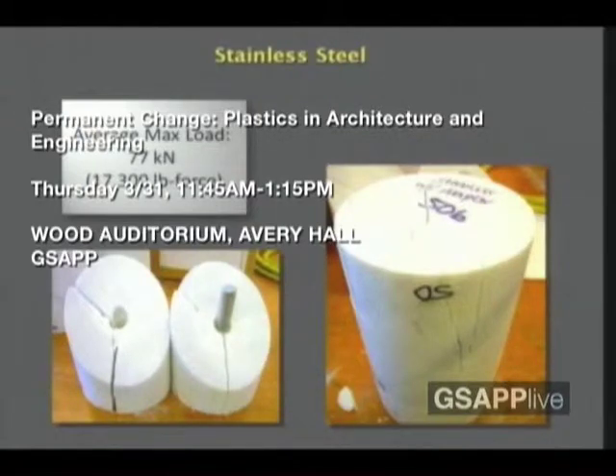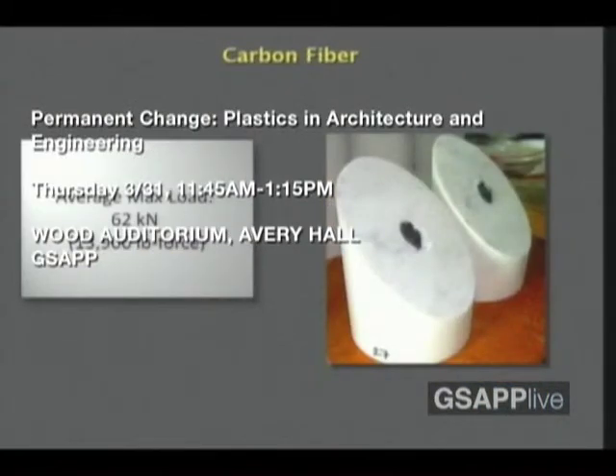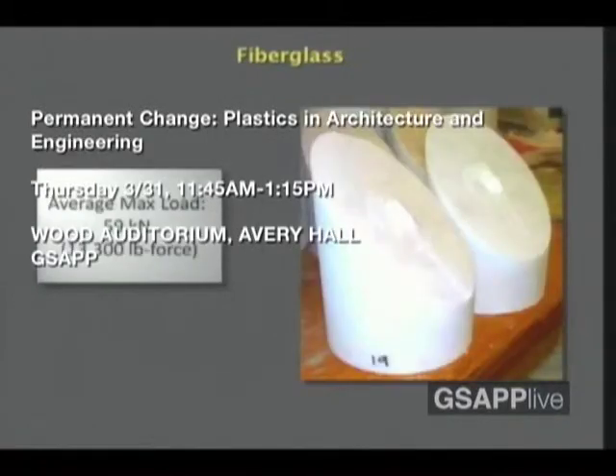And yet, over and over again, we've been using stainless steel for repair of marble and other stones in both indoor and outdoor environments. Here's carbon fiber. We eventually shear the fibers, and the whole joint is completely intact. We do get a few cracks with carbon fiber because the modulus is slightly higher than marble. And here's our fiberglass. Again, we just shear that pin. Very, very high force, by the way, is required to actually bring about failure. But nonetheless, none of that is transferred, at least in these experiments, into the marble itself. So if our sculpture falls off the platform yet again, and it breaks at the arm, hopefully the two pieces will be intact.